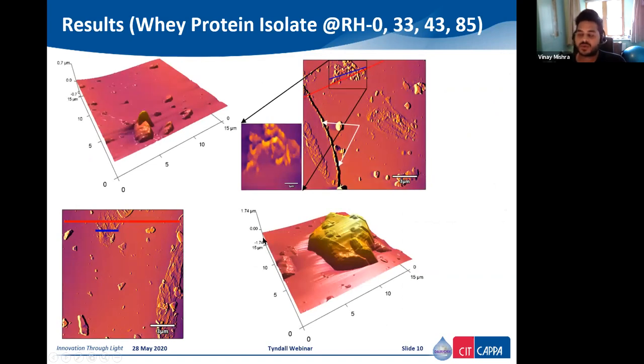Comparing this result again with WPI, that is whey protein isolate, I'm showing four relative humidities. And you can see it's more smooth as compared to skim milk, as compared to the previous results. It appears more smooth. There are more fragments on the surface of these powder particles. I'm not sure, as AFM is not for chemical composition analysis, what these small peaks are. Probably it's whey protein orientation, but I'm not sure at the moment. But you can see it's completely different from MPC and SMP. We have more fragments attached on the surface of these powder particles, but still they are smooth as compared to the others.